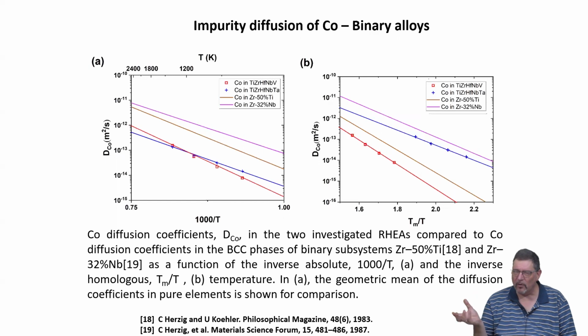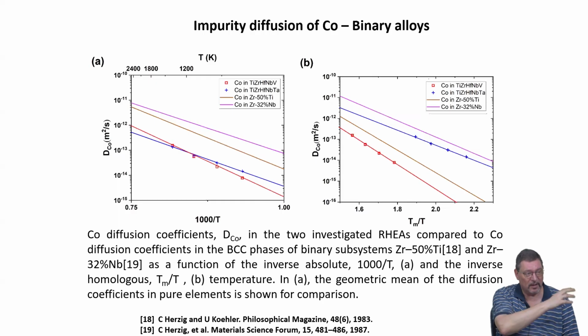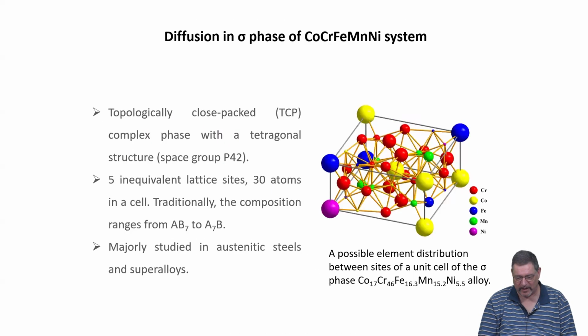Depending roughly on how we set up the comparison, we can see that there is either a deceleration or an acceleration of diffusivity. In the end, it's within 1 to 2 orders of magnitude, and this comparison involves either a pure element high entropy system or high entropy system and some geometric mean coming from the pure systems, and that is certainly bound to a variation of a few orders of magnitude.